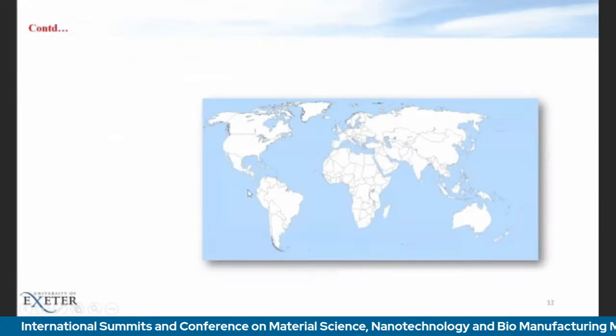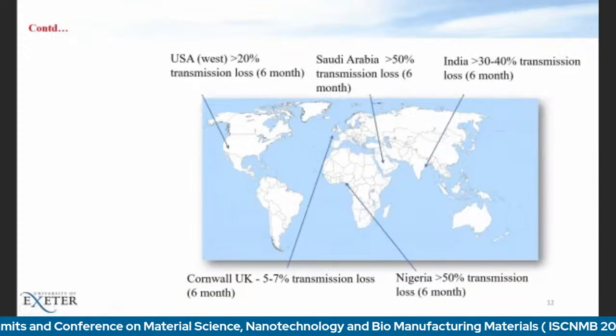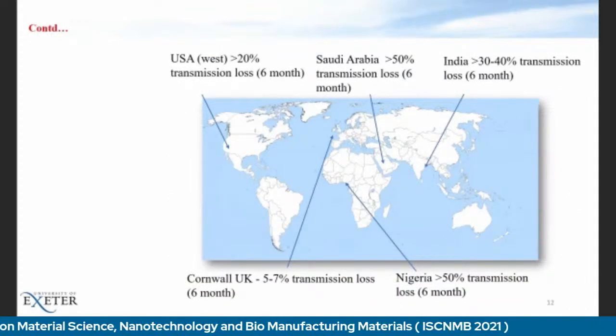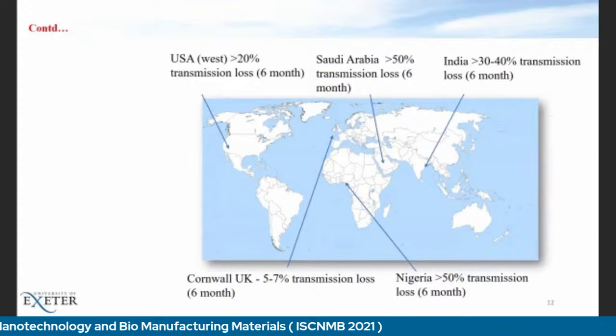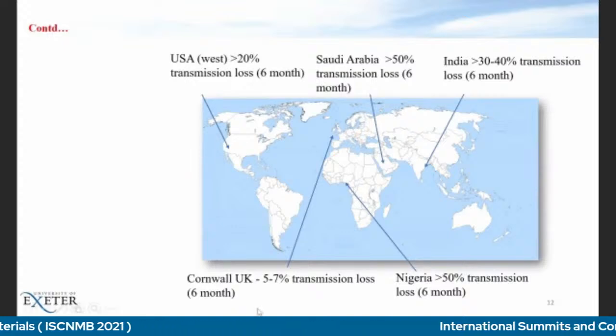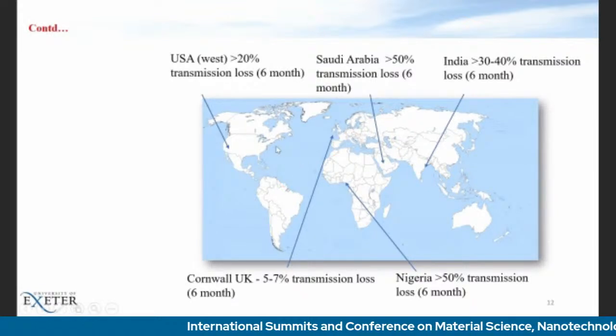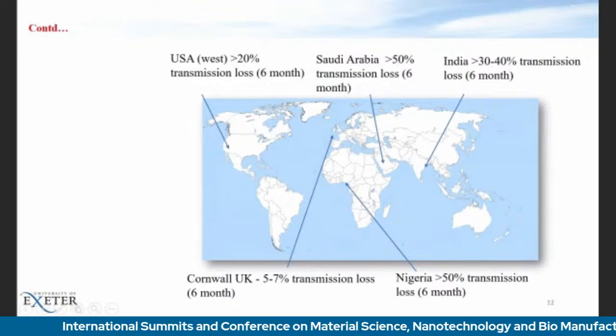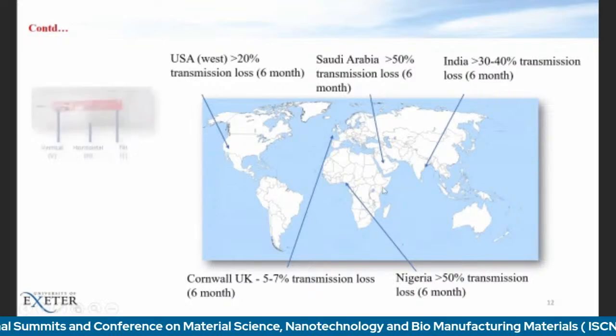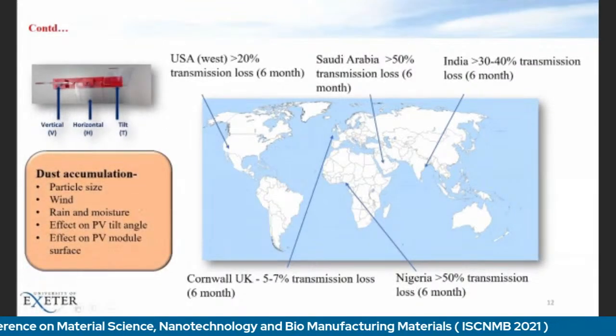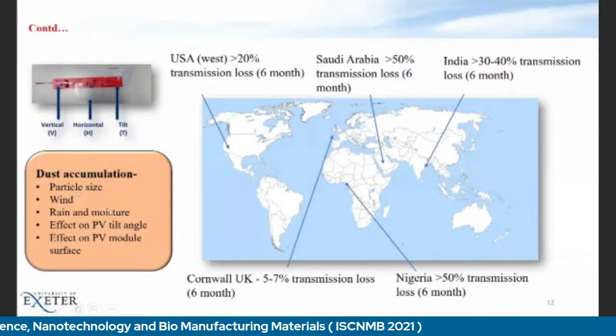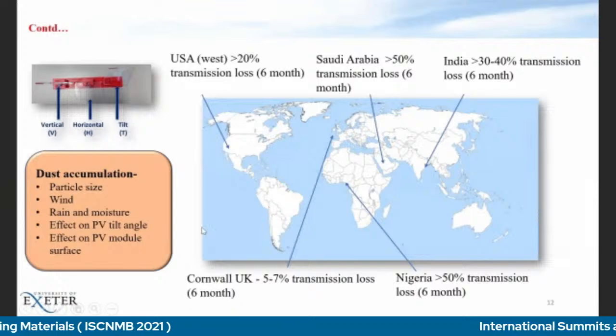Now, what is the solution? Globally, currently I am doing research throughout the globe to find out the impact of dust, and we found that not only in a very clean area like here, where it is 5 to 7% if we don't clean, but also in other places such as US, Saudi Arabia, Nigeria, India, it's over 50%. Dust deposition has different impact depending on the particle size, wind, rain, moisture, tilt angle, and the module surface type, but still we can see that there is an issue with this dust deposition.